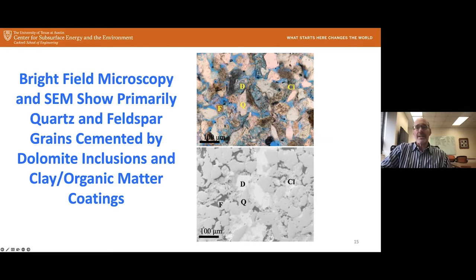When we look at this under SEM, because the dolomite has a relatively high iron content, we can see that it really shows up well. And we can see how it tends to fill pore spaces. And so it's one of the cementing minerals within this matrix. A lot of these dark little spots are clays. And so they also provide cements between grains as well, but not as much as the dolomite. So that would be a difference between the Mount Simon and the Bandera gray.